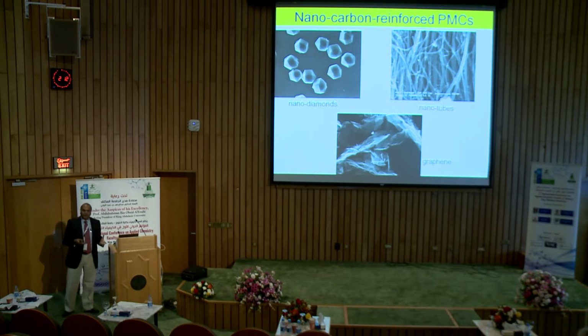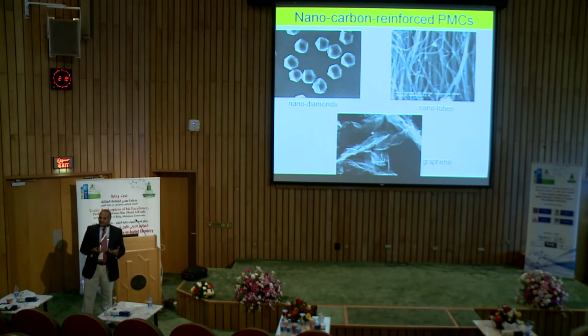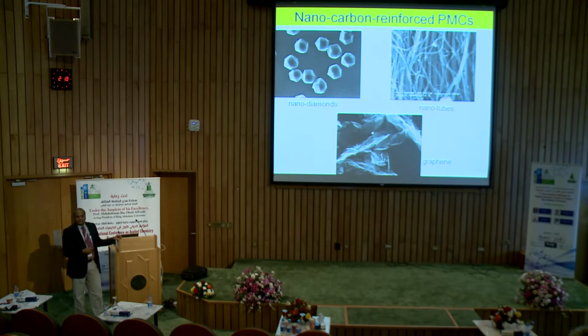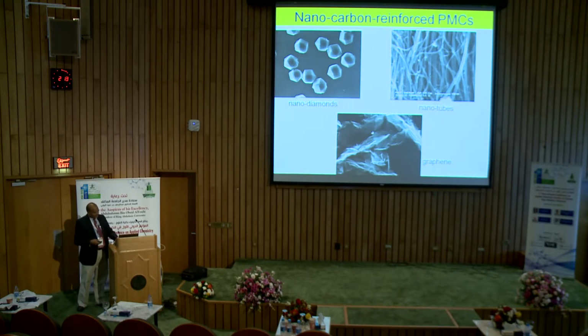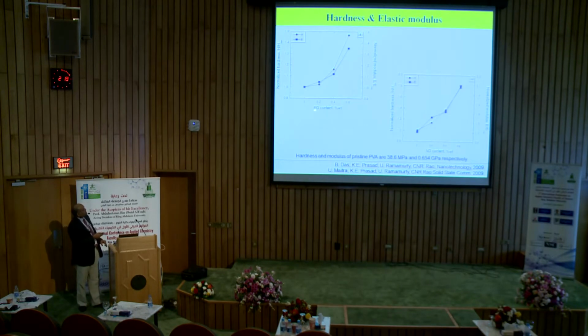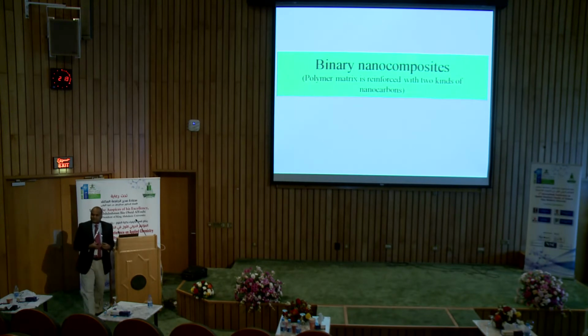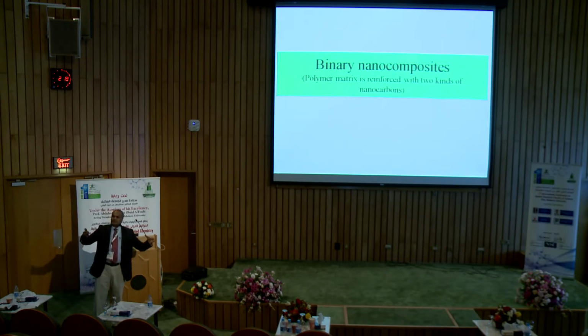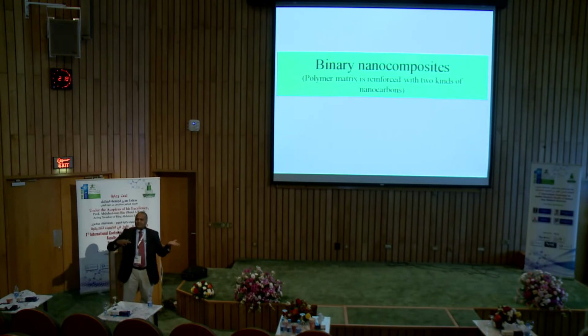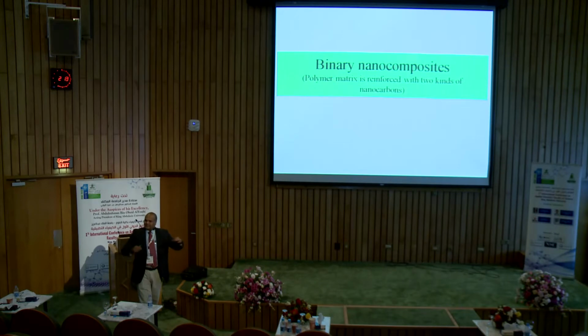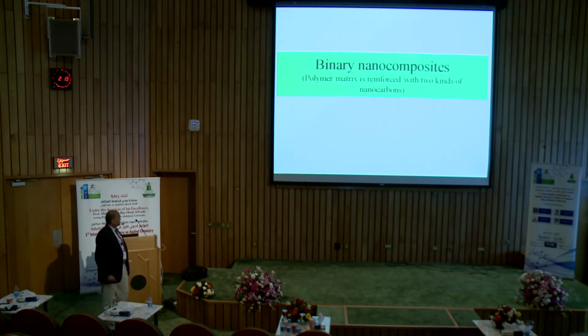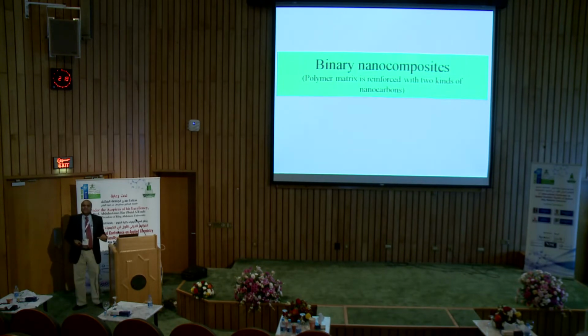So when you put these into a polymer, the way they interact with the polymers will be different. You can think that the fibers will align along with the nanotubes, so you will have a different response than with nanodiamonds. For example, if you put only graphene or nanodiamond, the increase is like this. It's quite significant. But what if you try to put 2 different things? Because when you put graphene, it's a 2-dimensional surface, the polymer chains can attach to it on a surface. Whereas if you put nanotubes, they can align along with the polymer chains. So if you put them together, would you get any synergy?